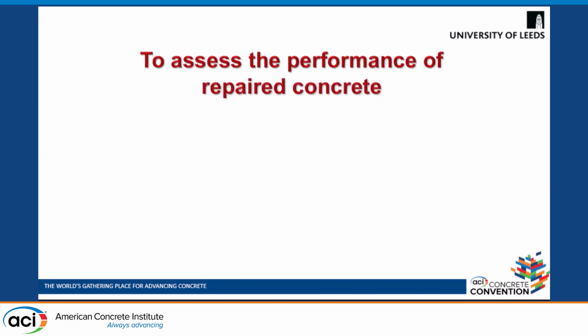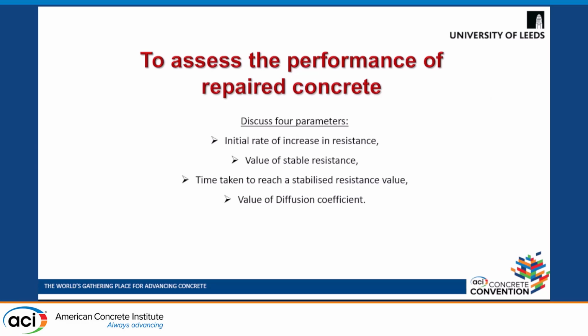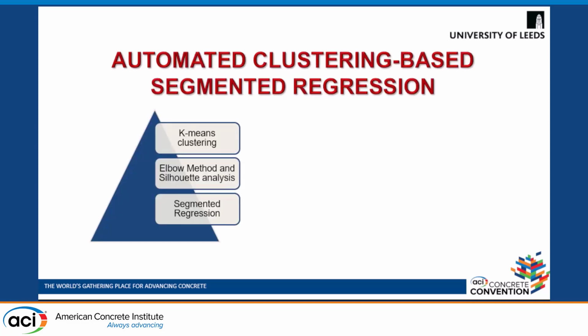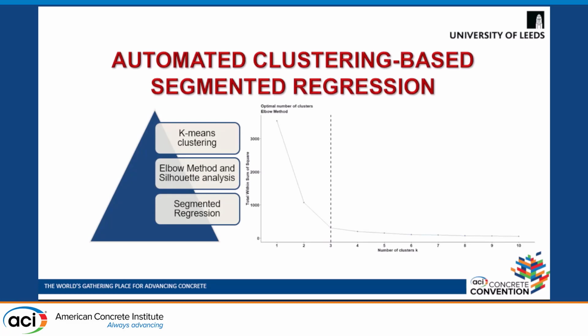To assess the performance of repaired concrete, it is essential to discuss four parameters: initial rate of increase in resistance, value of stabilized resistance, time taken to reach a stabilized resistance value, and value of diffusion coefficient, for which we are using clustering-based segmented regression. The first step is to use an elbow method, which is based on the k-means clustering algorithm. In this method, different values of k are run in the algorithm, and it identifies the optimal number of clusters using the within sum of squares approach, and it shows that there are 3 clusters in the data set.